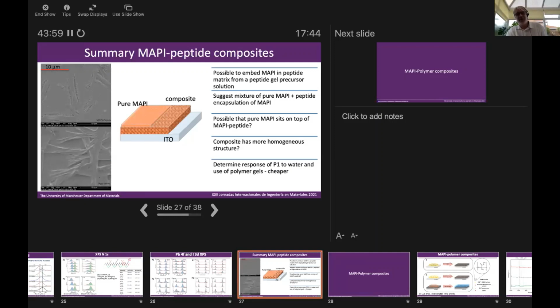A peptide gel mixed with a precursor solution, and we can spin coat this. We suggest that there's a mixture of pure MAPI and also some peptide encapsulation. So we've got some SEM images here. This is the scale bar up here. This is the peptide present. This is the pure MAPI.